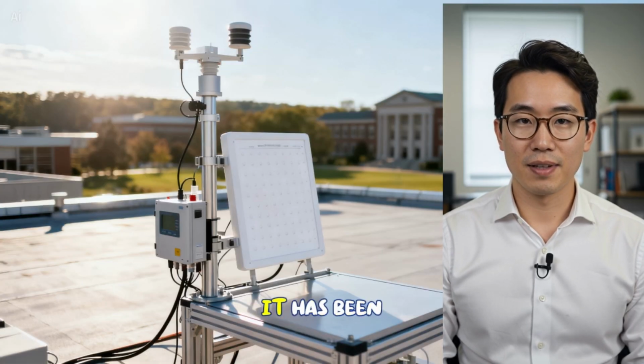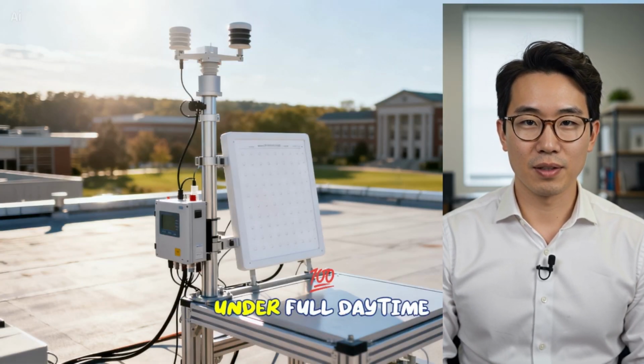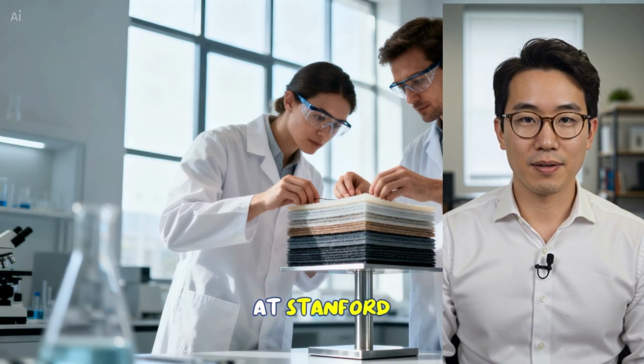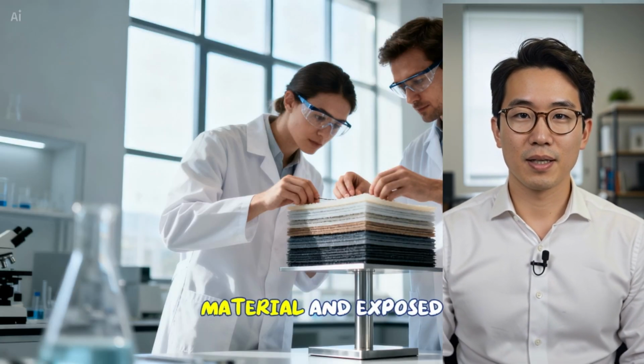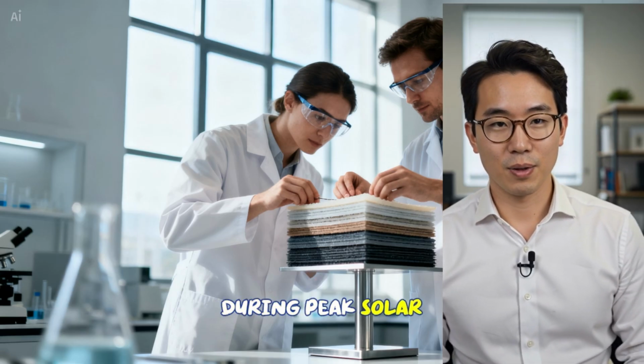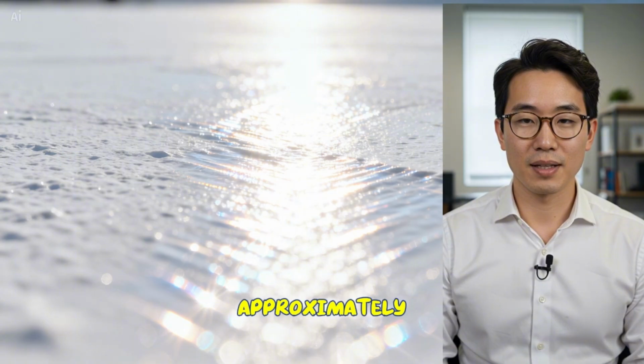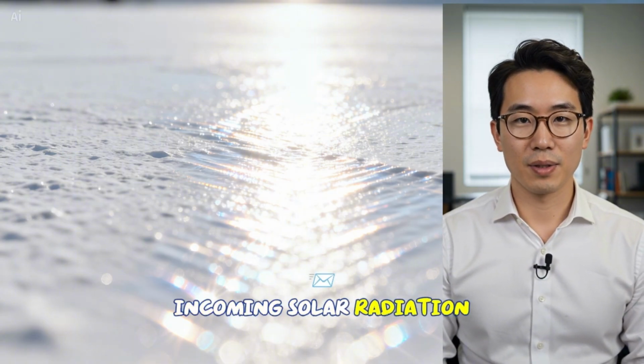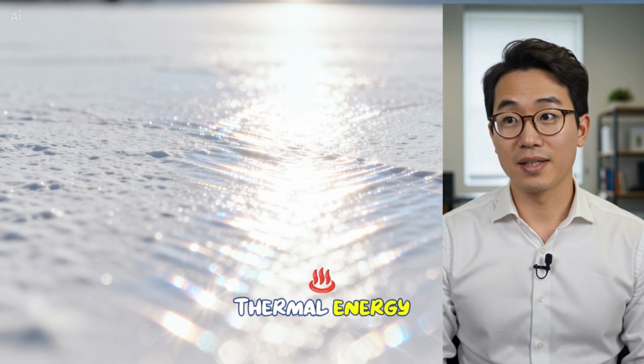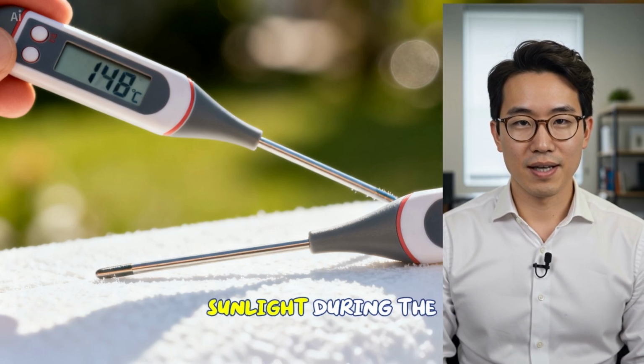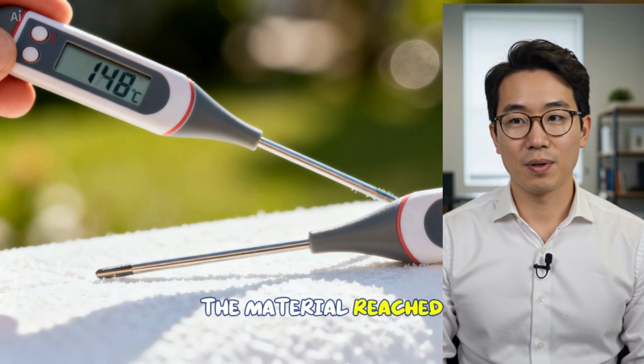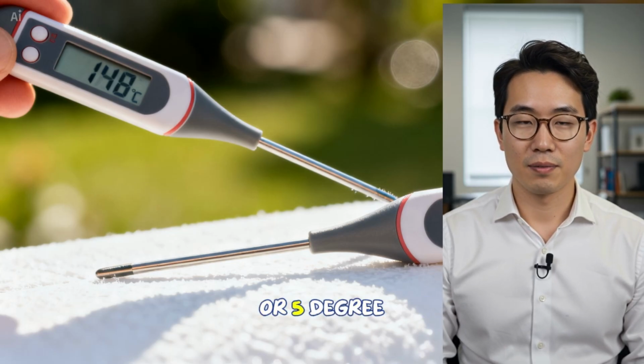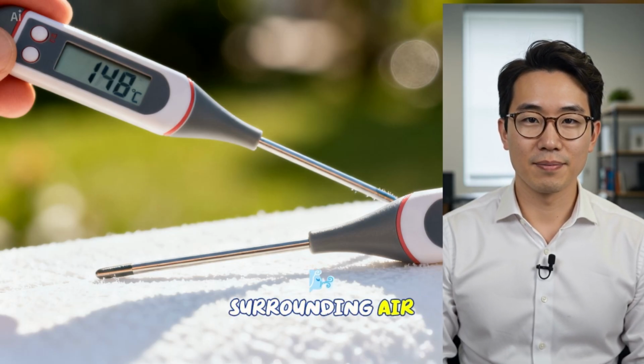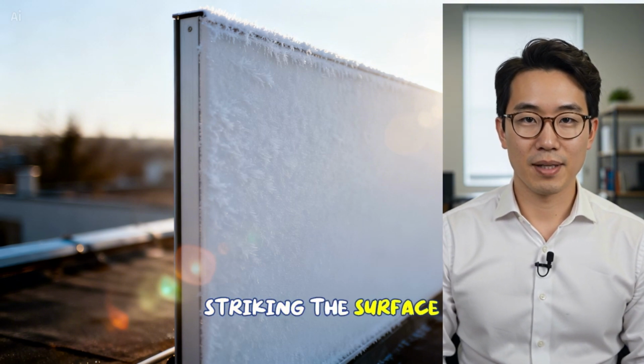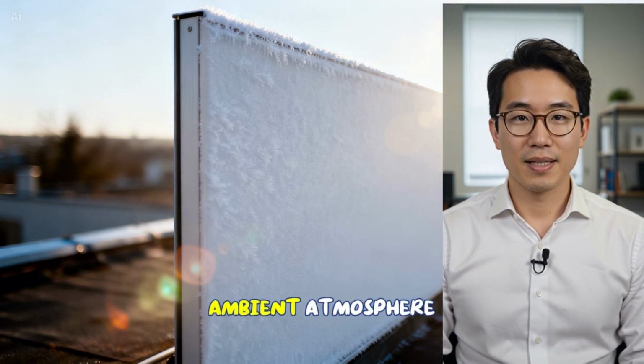This outcome appears counterintuitive until the role of the space-facing infrared pathway is understood. This is not theoretical. It has been tested in real-world conditions on a rooftop under full daytime sunlight. A research group at Stanford University constructed a specially engineered layered material and exposed it outdoors during peak solar intensity. The surface reflected approximately 97% of incoming solar radiation while simultaneously emitting thermal energy efficiently through the atmospheric infrared window. Their published findings were significant. Under direct sunlight during the brightest period of the day, the material reached a temperature approximately 9 degrees Fahrenheit, or 5 degrees Celsius, lower than the surrounding air. The sunlight was still directly striking the surface, yet it remained significantly colder than the ambient atmosphere.